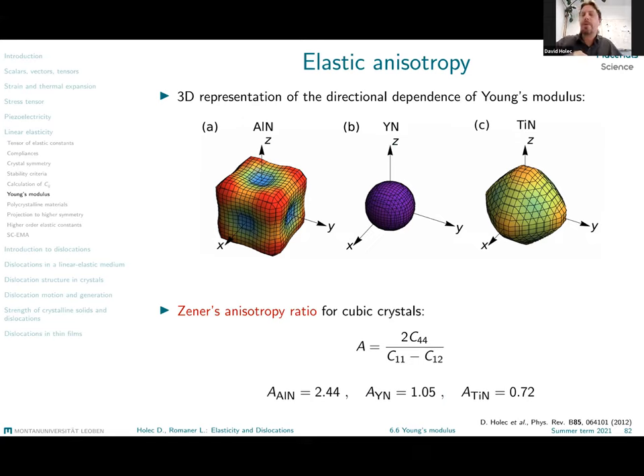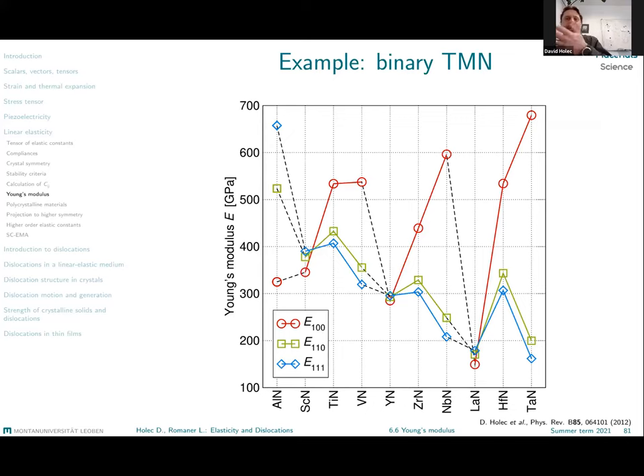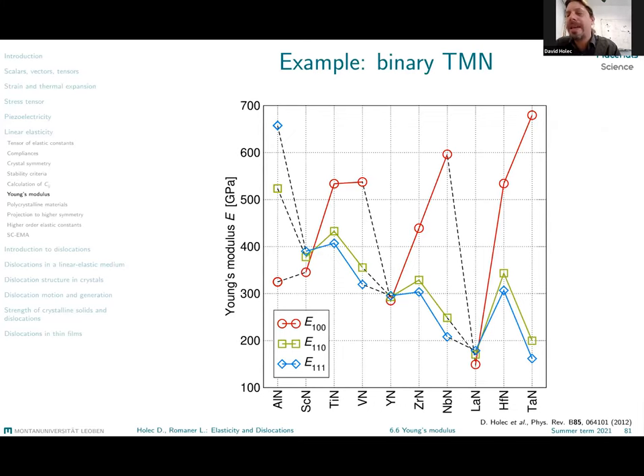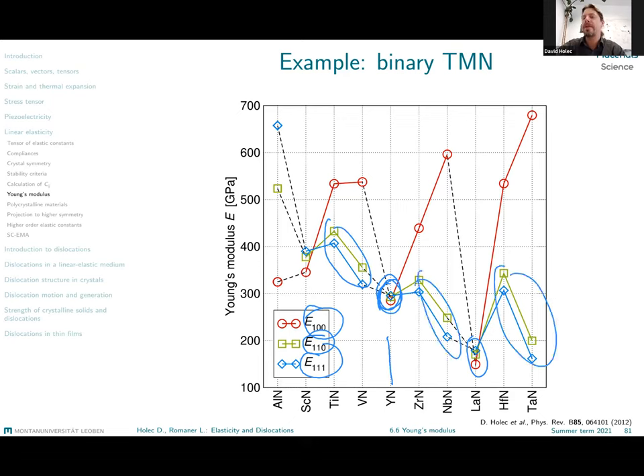Now, though these colorful blobs are very sexy and nice for publications, it's hard to read out the data out of them, and the data would then be conveniently shown by showing the Young's moduli in different crystallographically important directions. So here we have the values in the 100, 110, and 111 directions. And once again, look at yttrium nitride, an elastically isotropic material: the values are overlapping. They do not strongly depend on the direction in which we measure the Young's modulus. Same is true here for lanthanum nitride, whereas for all other transition metal nitrides, we get the same type of behavior, that the 100 direction is the stiffest. And the aluminium nitride is now the opposite one. There the 111 direction is the stiffest one.